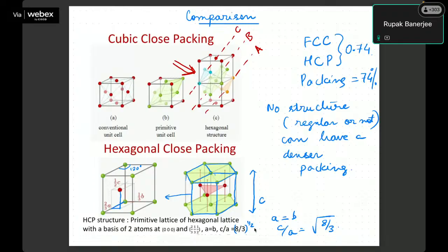And another thing which is important is that you probably also know that A is equal to B, but the C by A ratio is actually given by root over 8 by 3. This is also actually a small interesting calculation. It's actually just geometry and mensuration. That's all you need. You can just look at where the atom of this position is, and you can easily figure out a relation between the C value and A equal to B. So this C by A ratio is root 8 by 3. This is very well known for hexagonal close packing, and you can also calculate that using simple geometry. So hexagonal close packing and FCC are important crystal structure configurations, because there are no structures which can have a more dense packing.